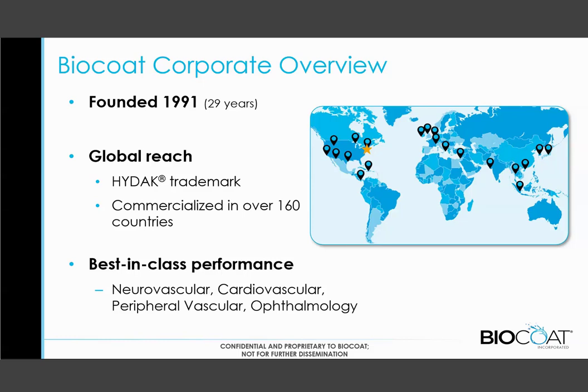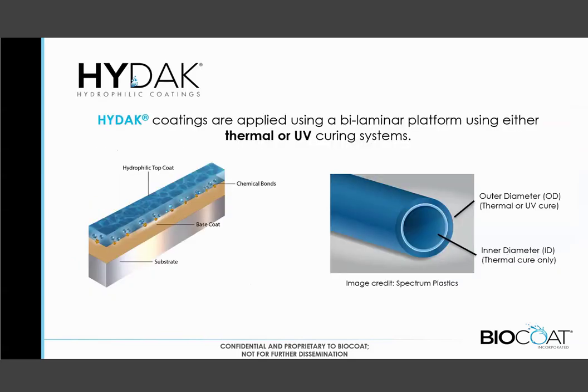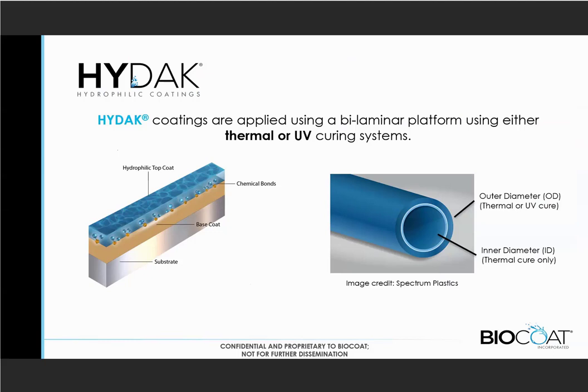Not to get too much into the details of the coating itself, but we do operate from a bilaminar platform. And Biocoat is one, if not the only company in the world that offers both a thermal curing system as well as a UV curing system. And what you see on the left is essentially how the process is put together. So we have a substrate, and the base coat that goes onto the substrate is a hydrophobic base coat that, in my words, not technical words, normalizes the substrate and enables us to put a chemical bond for the hydrophilic top coat that comes on after that point. And that is either heat cured or UV cured. The interesting thing about heat cure, of course, is that you can coat both the inner diameter as well as the outer diameter. And for UV curing, of course, that's a line of sight cure, so that is operating really only in the outer diameter dimension of the products that are available.